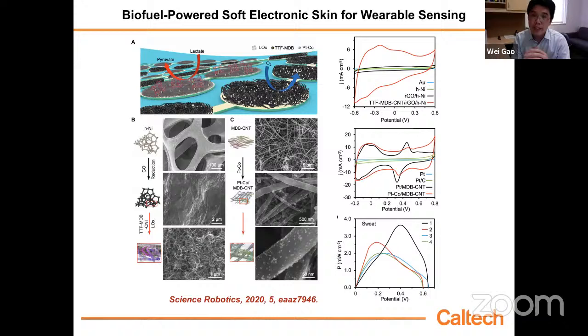For the cathode side, we use a platinum cobalt alloy nanoparticle doped carbon nanotube network, which also gives us very high surface activity, as well as, as we talk about later, stability improvement. Overall, we get very high power from human sweat. It's by far the best from this untreated human body fluid, as you can see here. We can get up to 3.6 milliwatt per centimeter square. In a very small area, we can continuously get over 3 milliwatt.